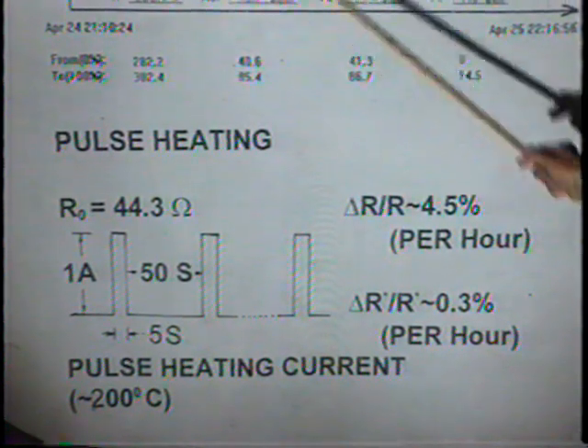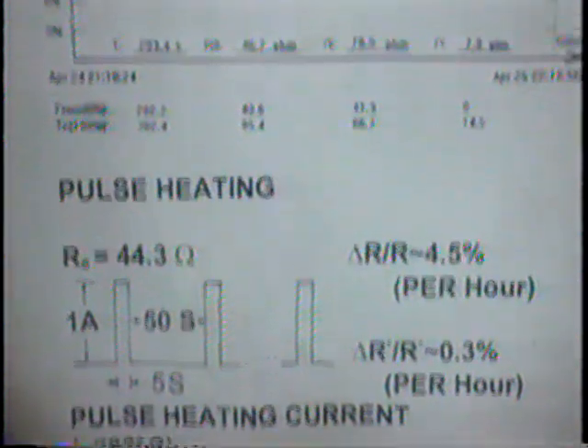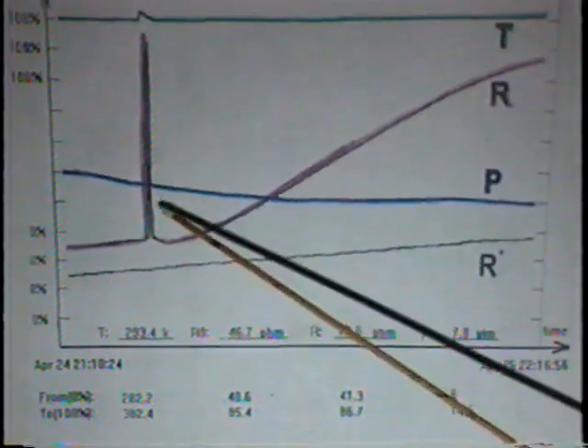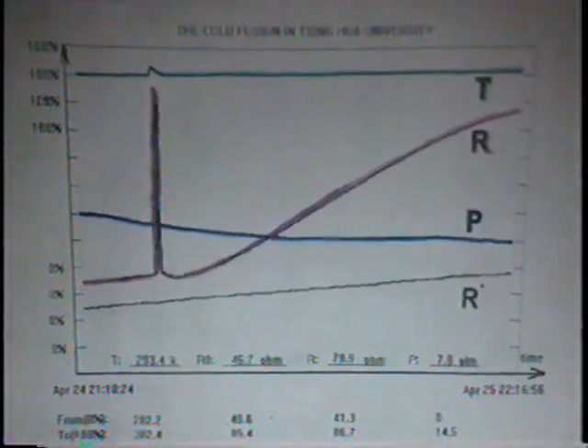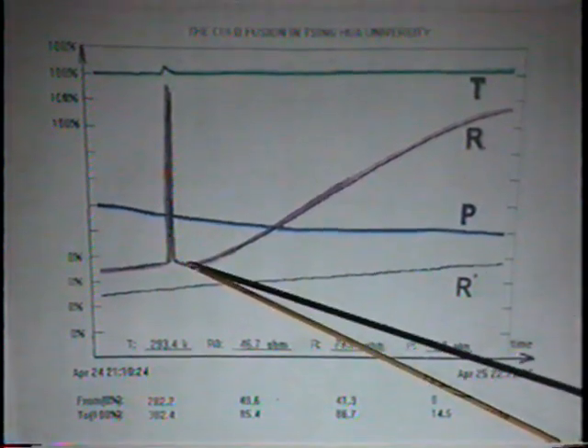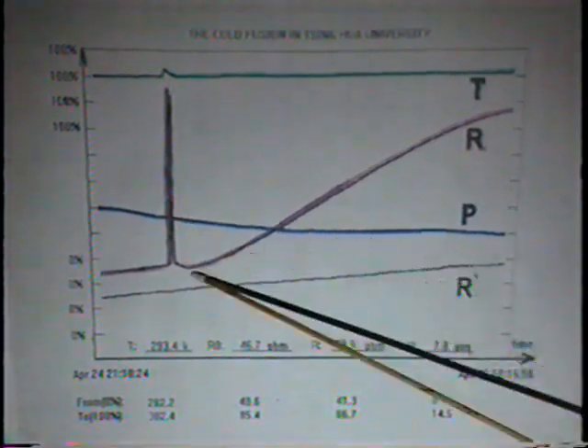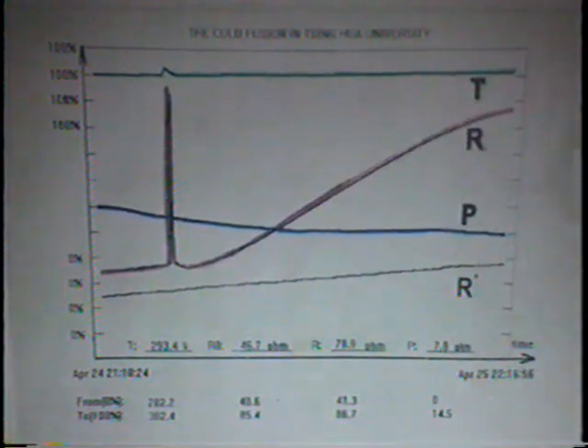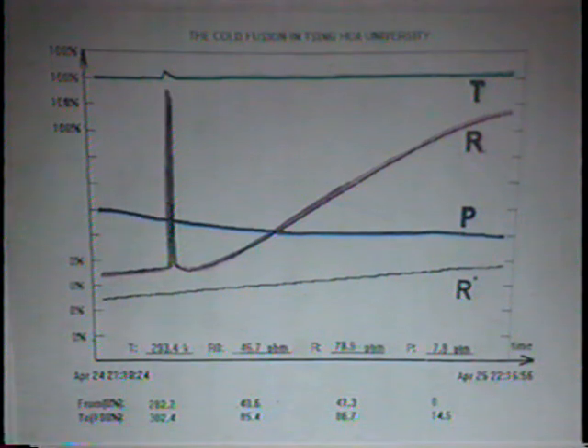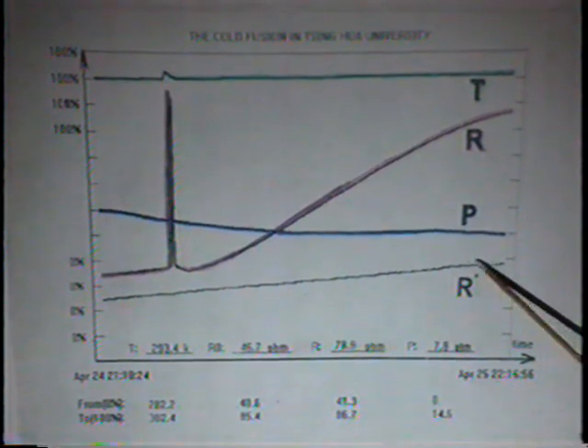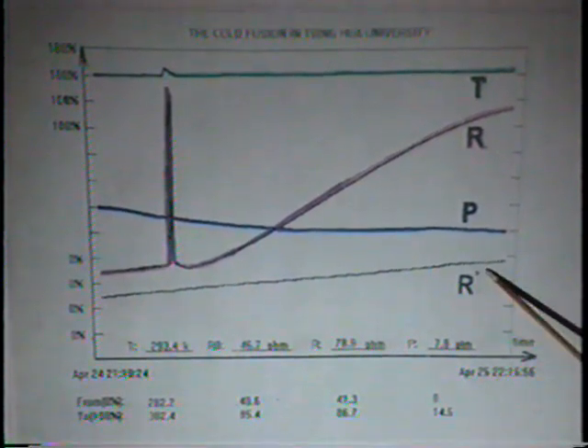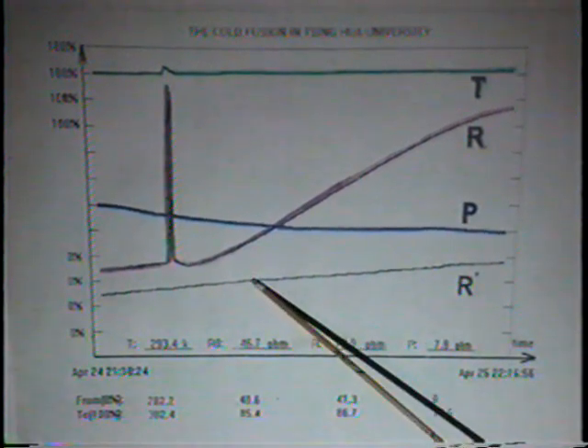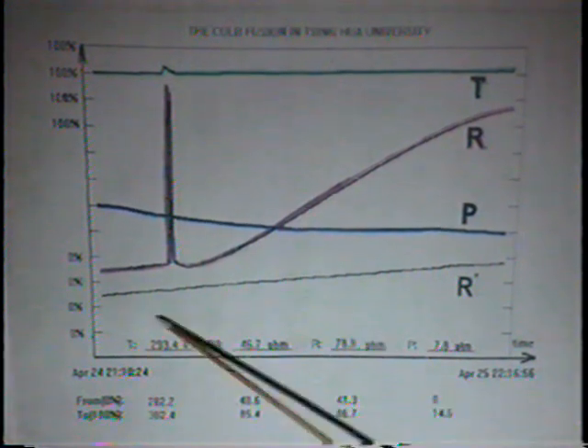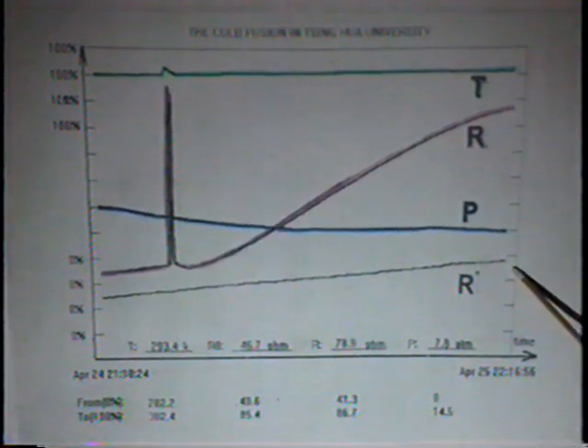This red one is the resistance ratio. This period means pulse heating. After pulse heating, you see the pressure drop, the resistance ratio goes up, the temperature stays the same. He did a control, put the same palladium wire in the same vessel, that's R star, but this one has no pulse heating under the same condition. The loading rate is much smaller.